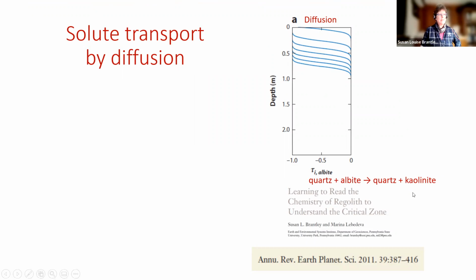So if you run these really simple, well, they're not that simple models, with quartz plus albite going to quartz plus kaolinite, we typically make plots of concentration of whatever's dissolving. So, concentration of albite on this axis and depth on this axis. If life was really simple, we could just plot concentrations, but we often normalize, because if you remove one element or one mineral, the other mineral will become more concentrated. So most of my plots will be what's called a mass transfer coefficient. It's a normalized concentration, and we normalize it using the concentration of albite in the original parent rock and some immobile element or immobile mineral composite or concentration.